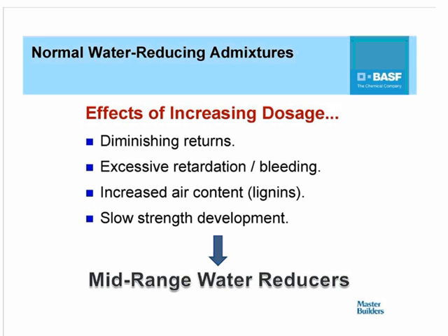Now, the typical dosage ranges of these admixtures will be anywhere from about 2 to 5 fluid ounces. And in some instances, as we go to the higher dosage levels, 4 to 5 ounces and beyond, we find that you have diminishing returns with respect to additional water reduction. However, as you increase the dosage, you also increase the potential for retardation as well as bleeding. And with the water-reducing admixtures that may be based on lignins or lignosulfonate salts, as they're more commonly known, you may also run the risk of increasing the air content of the concrete. Now, obviously, all of these can have an impact on early age strength development.